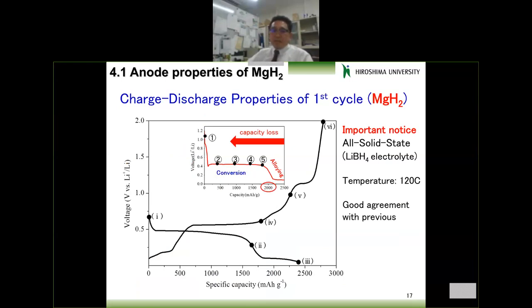And we start from this. And then this is magnesium hydride, and we try to get some conversion reaction with lithium ion. And then there is one big plateau, and this is the plateau. And then a second plateau is also observed. It's quite a similar result to the previous Nature paper.